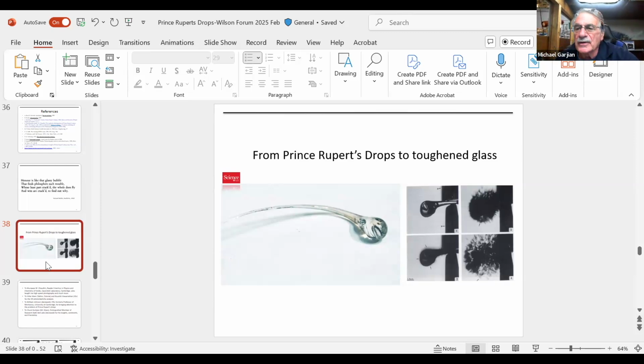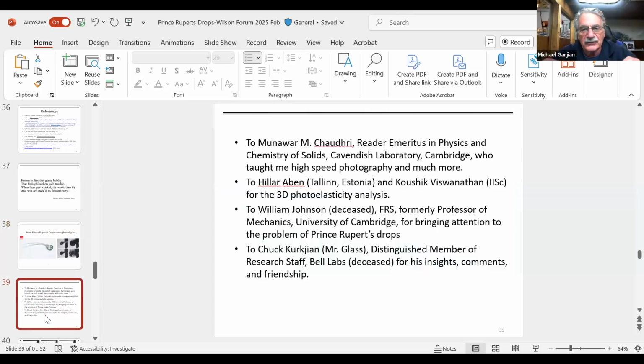I might be able to help here because I was involved very deeply with glass. It would be interesting to know how glass is tempered because you might not believe it's even possible. Basically, let's imagine a 4-foot by 8-foot sheet of glass being held at the top by self-tightening tongs, so the weight of the glass grips the tongs. You heat that entire glass plate from both sides with a heater to 1200 degrees Fahrenheit. That's the softening point of soda lime glass. At 842 degrees, that's the transition temperature, any stresses in the glass begin to become relieved. But at the 1200 degree point, the glass is becoming soft enough that those tongs actually make little divots into the glass.